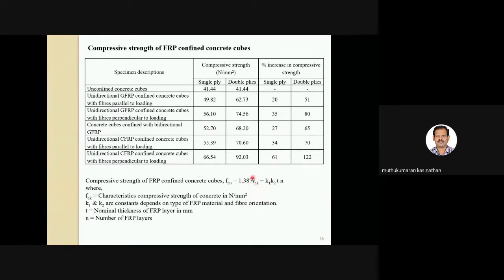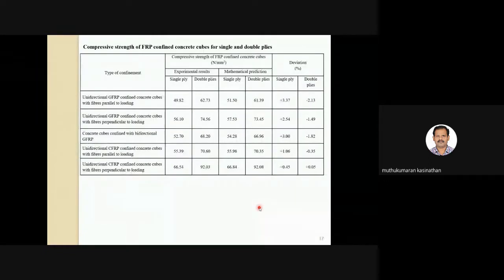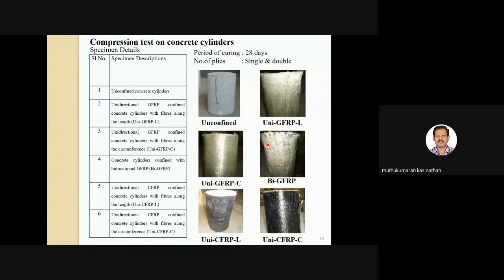1.38 times the square root of f ck, this is the conventional concrete, unconfined concrete characteristic strength. K1, K2 are the constants depending on the FRP material and fiber orientation, and T the nominal thickness of the FRP layers known to us, and N is the number of layers. So likewise, we have measured values and values estimated from this mathematical prediction, and more or less the error is less than 5%, so the equation is very well valid. So we just thought of developing an equation with the limited experimental data we have obtained.